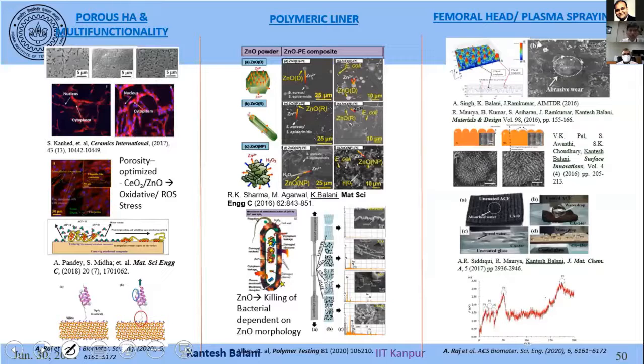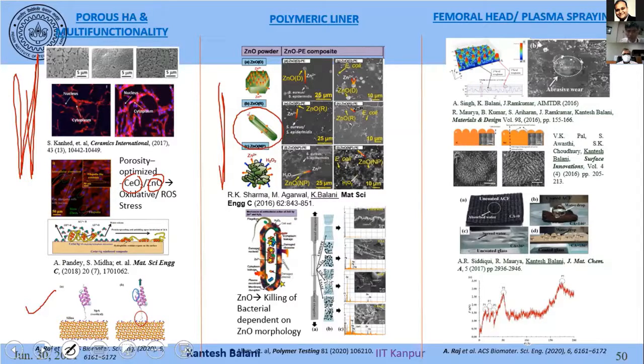We would like to get some sort of porosity in femoral stems and scaffolds, and there we can also add more functionality by adding zinc oxide, cerium oxide, or carbon nanotube. And this surface response again is very important. That's what we just saw. And for the polymeric liner, we can also change the morphology of zinc oxide. Right now we're using rods, but we can also tailor it to get some sort of antibacterial response. And then the other aspect is the femoral head. That's where we can get some hydrophobicity, some texturing done on the surface to obtain an appropriate tribological response. I'm just highlighting that this is more or less a summary of the direction we are working in.